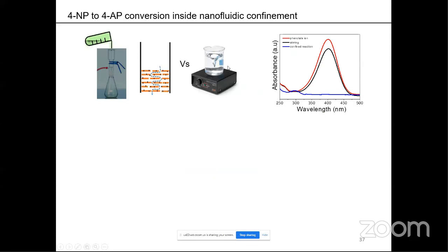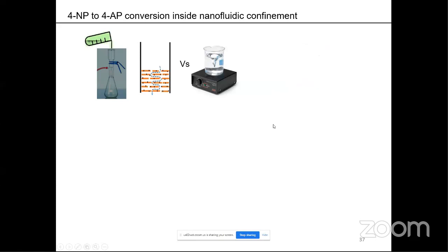Here you can see using 0.1 molar sodium borohydride. In case of stirring, the reaction did not go. It takes a long time, but within 1 minute, the confined reaction just took place and completed, with no intermediate left and no starting material left, and that itself came into products.